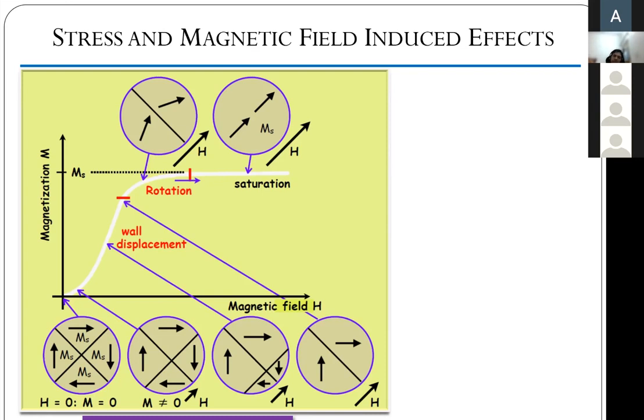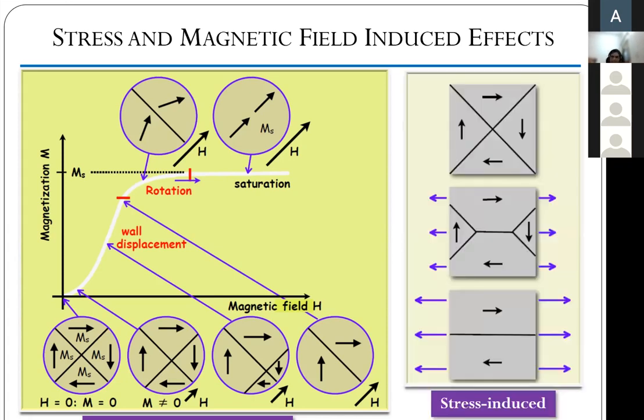In the process of domain growth and domain rotation, the domains also stretch. There is a shape change. Because we are causing this rotation, the domains have to realign themselves, and when that happens, there is a shape change, and that's the reason why we see magnetostriction. I also talked about the inverse effect, where stress-induced anisotropy is observed in the materials.